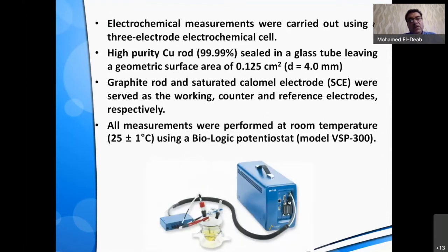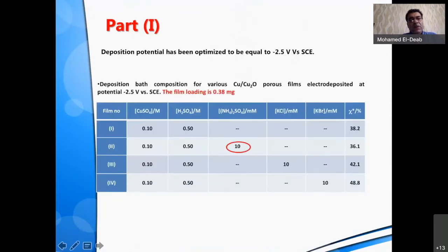We use a traditional electrochemical potentiostat system like this, and this is the electrochemical cell we used for the preparation of the different catalyst layers. For part one, we prepared copper foam in the presence of different additives. The main components of the copper deposition bath are copper sulfate and sulfuric acid, and in one experiment we just added some ammonium sulfate. In another, we added some potassium chloride and potassium bromide.